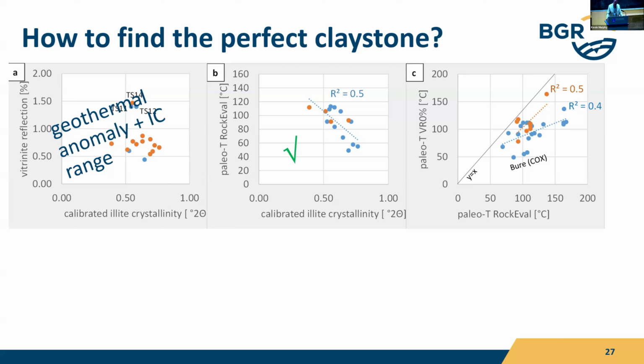If we compare the illite crystallinity with Rock-Eval, on the other hand, then this fits quite well. So that means that obviously both parameters, the Rock-Eval and the vitrinite reflection, which are commonly used to determine paleo-temperatures, are a bit tricky. When I look at values like 53 degrees or something, this value is not reflecting the error. Depending on which algorithm you use and which kerogen you find in your material, and you consider it with the vitrinite, you will have a significant range of paleo-temperatures. So the values derived from these methods have to be taken with care.